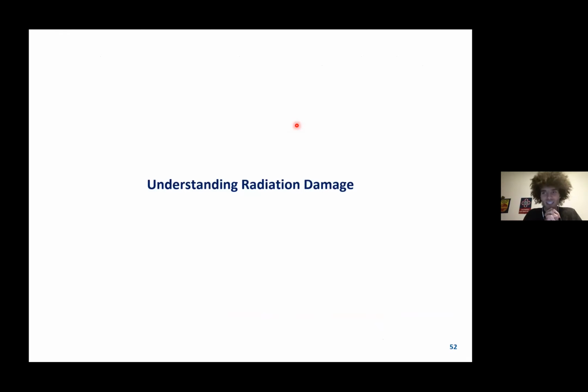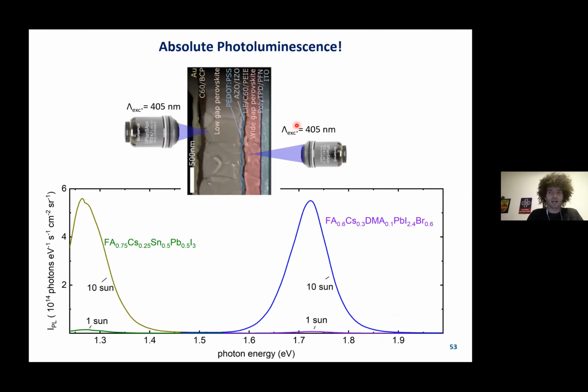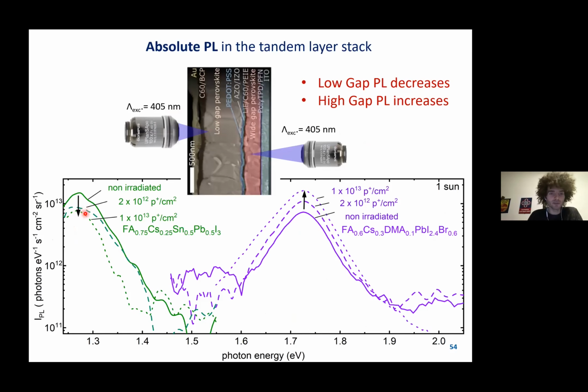All right. With that, I would like to come to my almost last part. Can we understand the radiation damage in such a perovskite tandem? And what I've been doing here is again PL. So I'm looking at the PL of the wide gap perovskite by exciting it from this side, and the low gap perovskite by exciting it from the other side. And you can do this, of course, after proton irradiation. And when doing that, I see that the low gap degrades in PL, while the high gap actually increases in PL. All right. I was quite puzzled by this result, honestly.